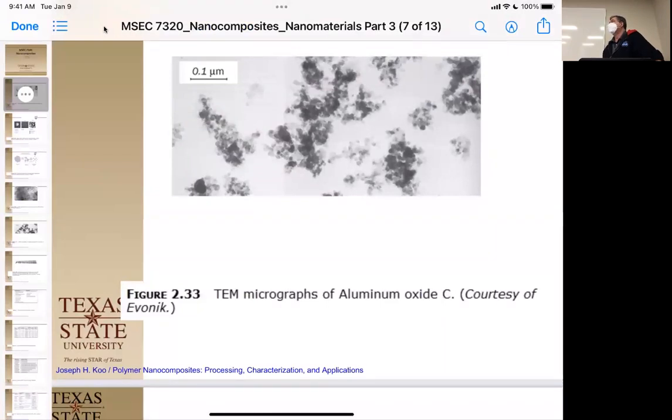They actually started this back in the 50s. You can make aluminum chloride and actually do a hydrothermal version or a flame version, and it produces the same level of, in this case, the flame versions produce low crystallinity, almost amorphous aluminum oxide, and can be used. So what do you care if it's silicon dioxide or aluminum oxide? Well, they'll have different compatibilities and different long-term effects on things like UV stability. So you can choose whichever one you want.